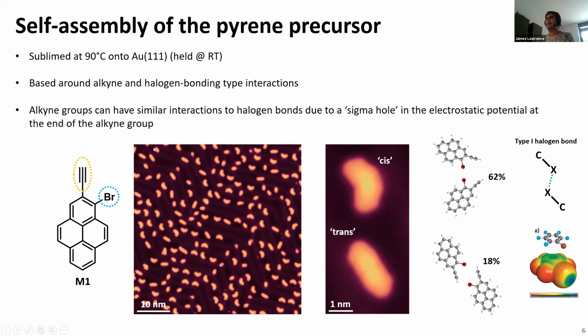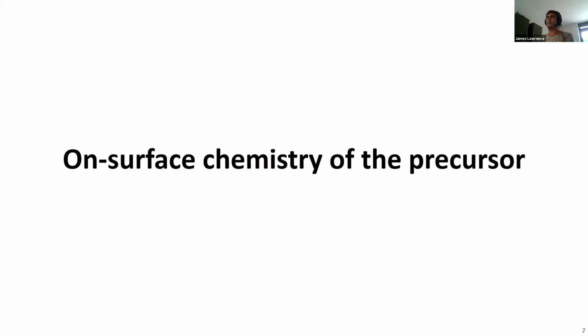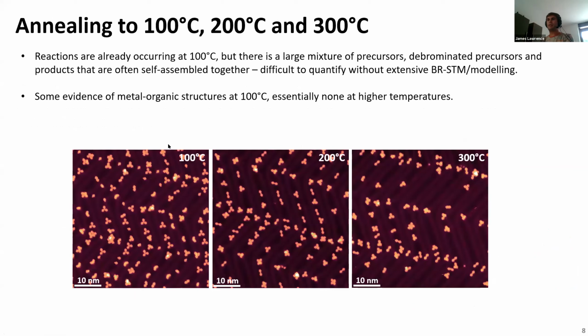So if we then heat this up to some quite large temperature steps of 100, 200, and 300 degrees annealing temperatures, we can see that when we go to 100 degrees, we can already start seeing that some reactions have occurred. However, there are still quite a significant amount of precursors and dehalogenated monomers and so forth. So we really need to look and focus on the 200 and 300 degree steps for the fully reacted